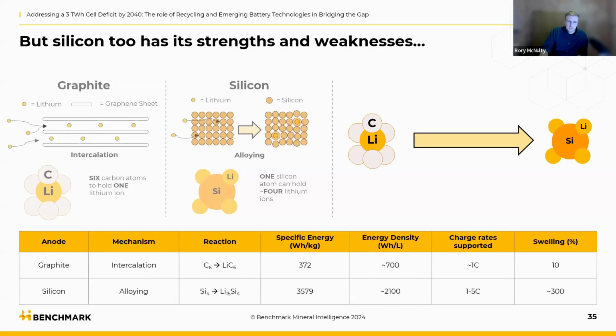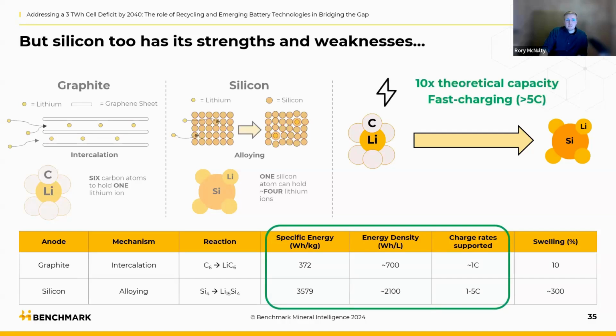And if we look at the positive aspects, what we see is that there's a 10 times theoretical capacity increase going from graphite to silicon. As I said earlier on, in a practical setting, it's closer to 2 to 3 times that we're likely to see. And silicon can also enable fast charging. It's expected that a reasonable target for fast charging of these anodes would be below 15 minutes, with some in the market claiming charge times as fast as 3 to 5 minutes.